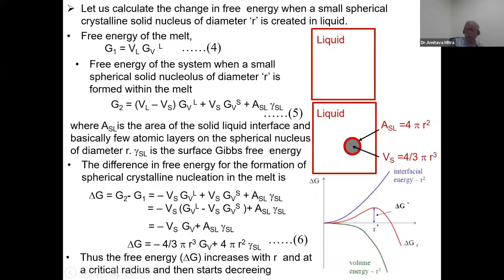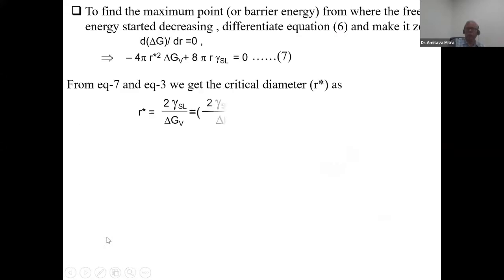So as you can see that this is the maximum. So what we will do, we will differentiate this equation and make it equal to 0. What we get is d(delta G) by dr equals 0, and from there we can get a critical radius r star, which is proportional to 1 by delta T. And what is delta T?